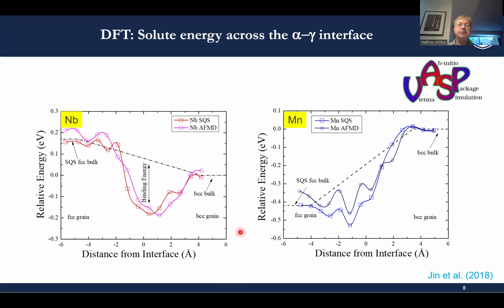So we basically know the binding energy to each individual site at the interface. And we can use these binding energies to estimate the probability that a particular interface site is occupied at higher temperature. And out of this, we can estimate what the enrichment of the solute, of this alloying element, at the interface would be as a function of temperature.